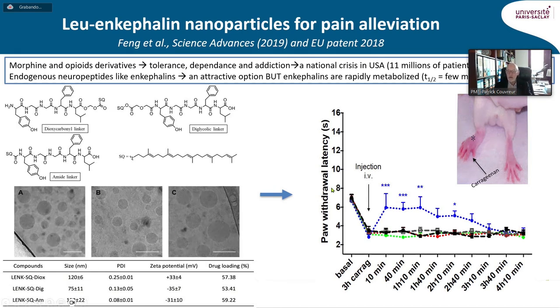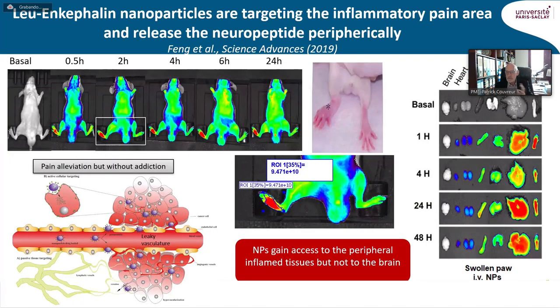And we have tested those nanoparticles on a model of inflammatory pain, which was induced by the injection of carrageenan in the right paw of rats, inducing a swelling of the paw, as you can see here, very painful. And after treatment with those leu-enkephalin squalene nanoparticles, you can see here in blue that we obtained a long-lasting pain alleviation that was not observed after the administration of the leu-enkephalin as a free molecule. And then to investigate the mechanism behind that, we have performed some imaging studies that you can see here after labeling of those leu-enkephalin squalene nanoparticles with a fluorescent dye.